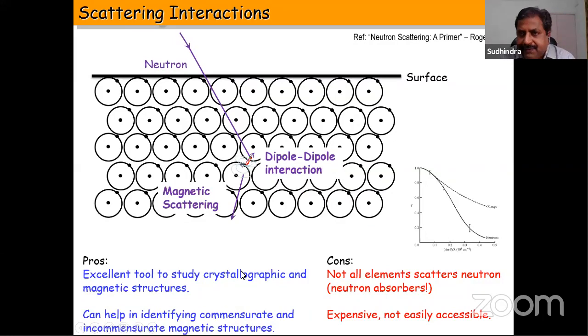Another aspect of neutron diffraction is that neutrons have a magnetic moment. The magnetic moment or spin of the neutron can interact with the unpaired electrons in the sample via dipole-dipole interaction and get scattered. That is called magnetic scattering. It makes neutrons an excellent tool for studying both the crystallographic structure and the magnetic structure. From the magnetic structure analysis, you can identify commensurate and incommensurate structures. But the disadvantage of neutrons is that not all elements are neutron scatterers. There are neutron absorbers also. And of course, neutrons are not easily available. They are quite expensive to use.